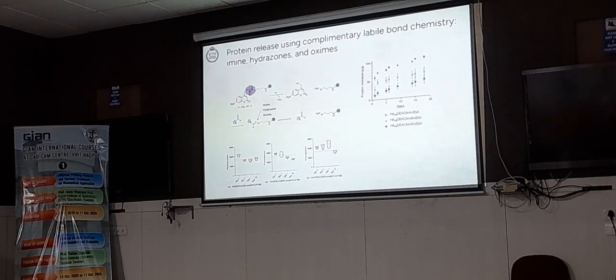And we also tried that. So this was with the BSA, which is quite a large protein. We also tried it with a smaller protein, if you know about that one. And it was the same thing. We could verify that we could functionalize it, attach it, and that it was released at different time points, just related to this equilibrium.